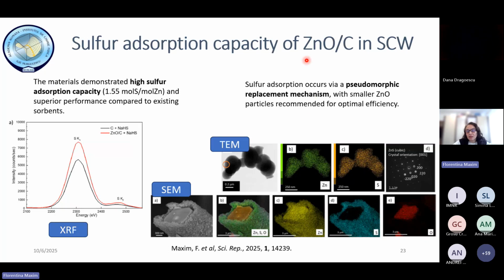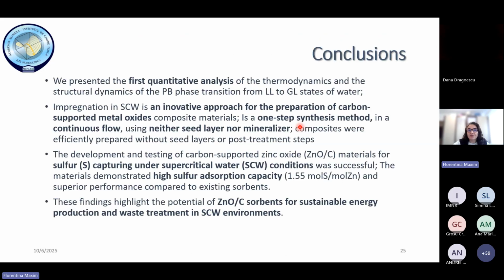We also tested the sulfur absorption capacity under supercritical water conditions, because we want these carbon-supported zinc oxide materials to function as sulfur absorbents, to overcome catalyst poisoning under supercritical water gasification conditions. And we managed to obtain a high sulfur absorption capacity, which is superior performance compared to existing sorbents that work under supercritical water conditions. This sulfur absorption occurs via a pseudomorphic replacement mechanism in which the zinc oxide nanoparticles deposited on the carbon fibers are more efficient for sulfur absorption. So in conclusion, we presented the first quantitative analysis of pseudo-boiling, both theory and experiment.